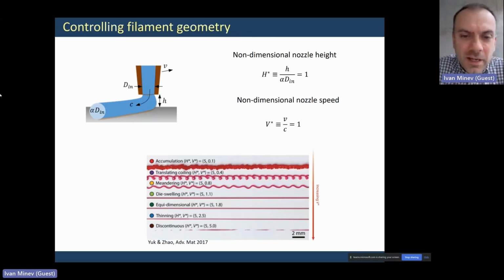And in this paper, it was explored how to produce wavy structures or even coils when you're printing from far away and going slow. We used this a little bit as inspiration to explore a different regime, when we are printing very close to the substrate. There are two parameters that have to be defined, the non-dimensional nozzle height and the non-dimensional nozzle speed. Basically, h star is equal to 1 when the height of the nozzle above the substrate is equal to its diameter, and v star is equal to 1 when the speed with which the material comes out is equal to the translational speed.